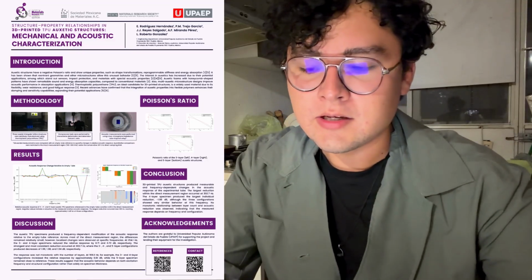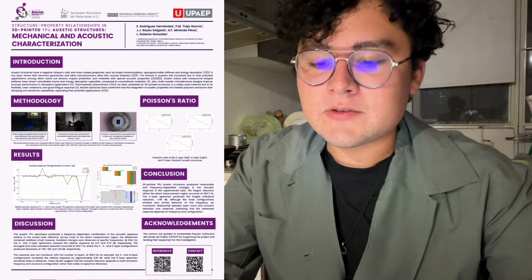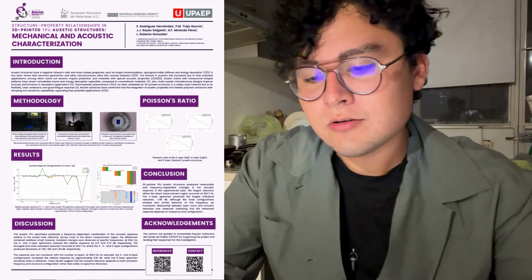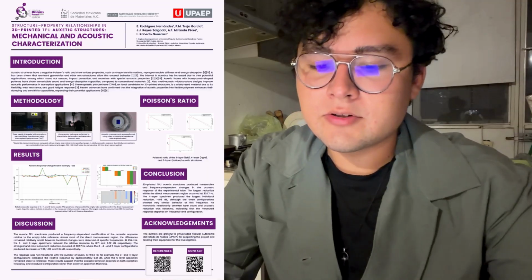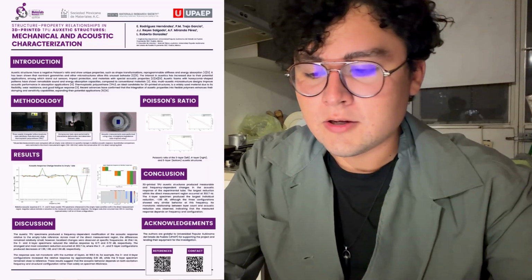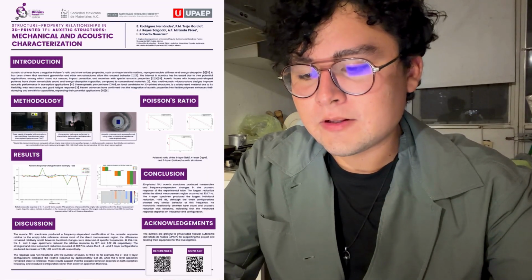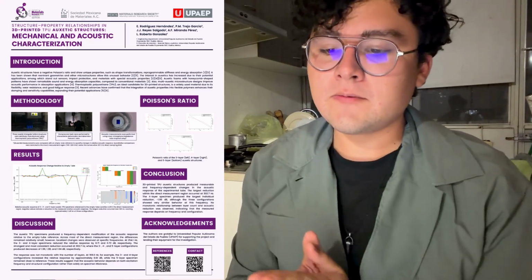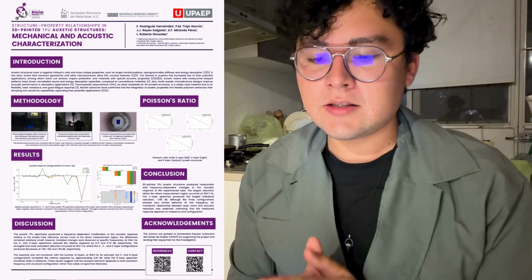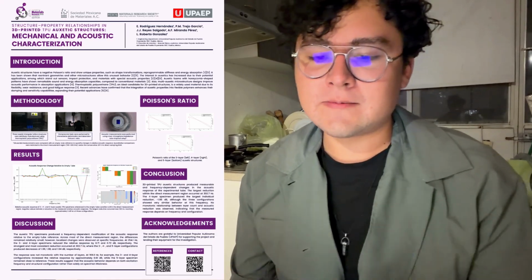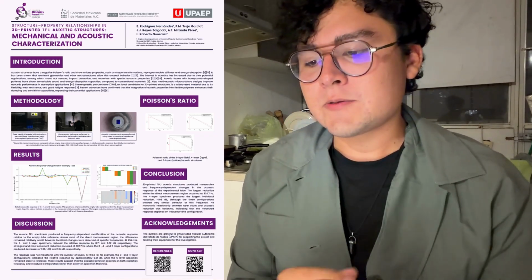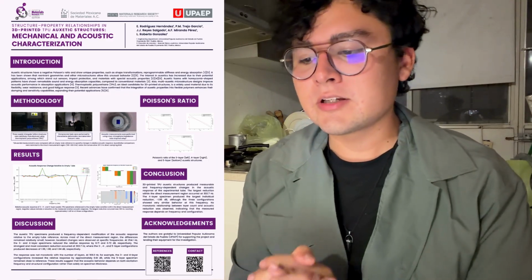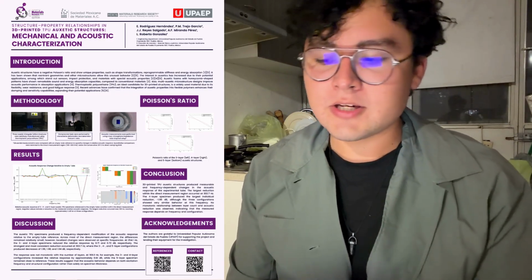0.71, 0.72 decibels, respectively. The most important result occurred at 303 Hz, where all the structures produced a reduction close to 2 decibels. The 3, 4, and 5 layer structures produced reductions of 1.96, 1.98, and 1.94 decibels, respectively. The response map shown here also helps us visualize that this reduction occurred consistently among the 3 configurations.